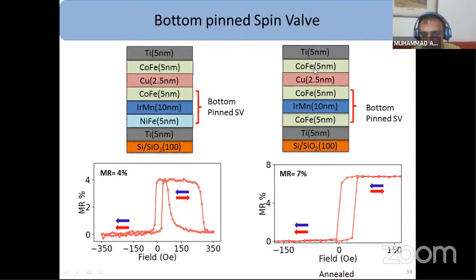I annealed this spin valve system at 170 for 30 minutes. Then I got an increased value of 7% in this case. The unannealed samples both have the same magnetoresistance. This implies that the seed layer does not have any effect on the magnetoresistance of the spin valve.